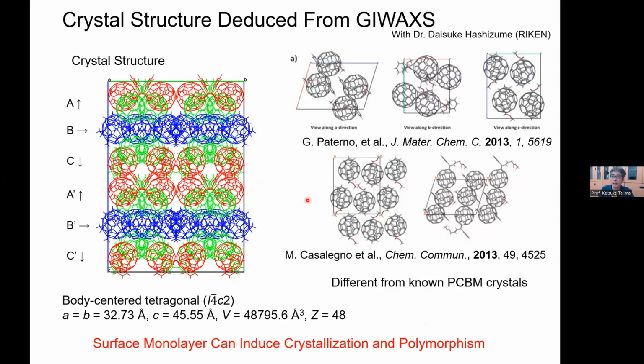By using the X-ray diffraction pattern, we can get some idea about the packing structure. We cannot solve it because the information from the film X-ray diffraction is too limited, but we still get an optimum structure to reproduce this diffraction image. This is a really unique structure. It has a very large lattice constant and 48 molecules in the lattice. Several crystal structures of PCBM have been reported, but this is very different from the others. That means the surface monolayer not only promotes crystallization from the surface, but also crystallizes this molecule into a different crystal structure. So it induced a polymorph from the surface.